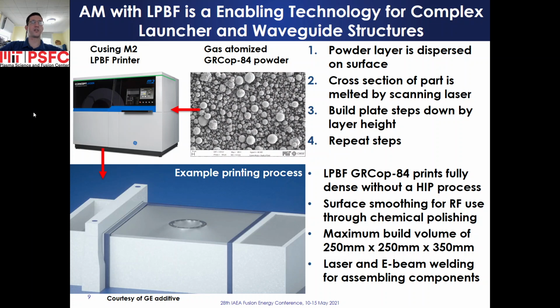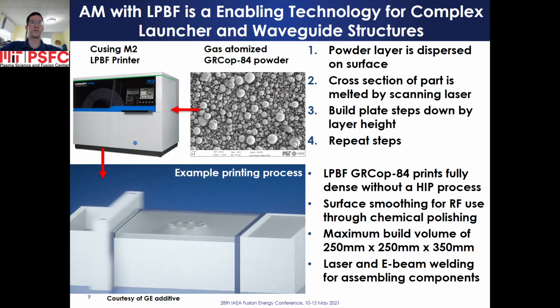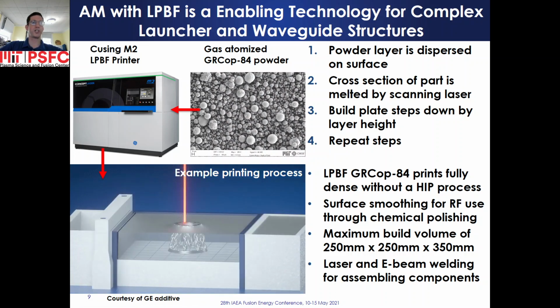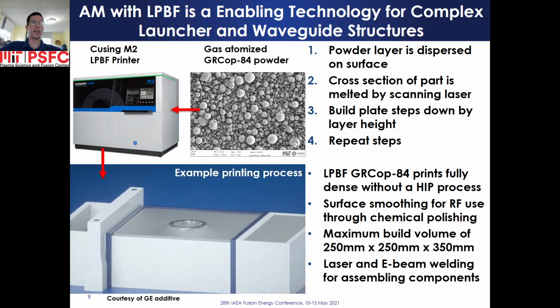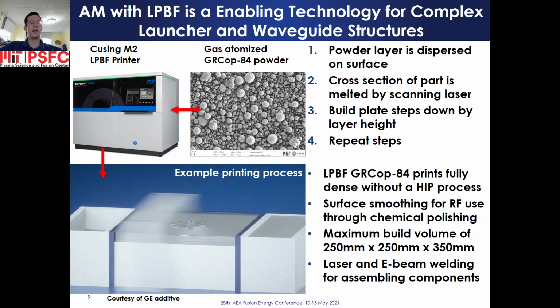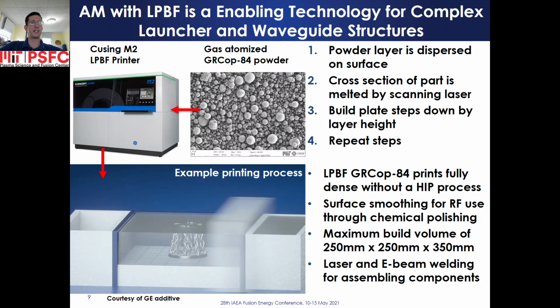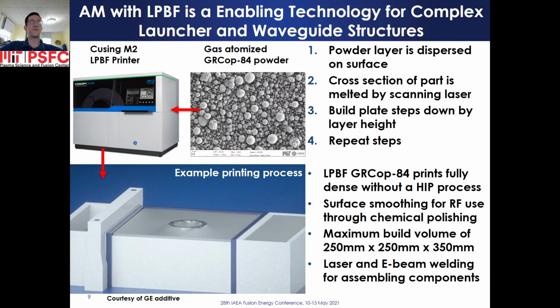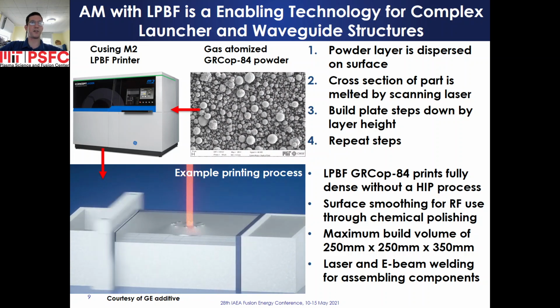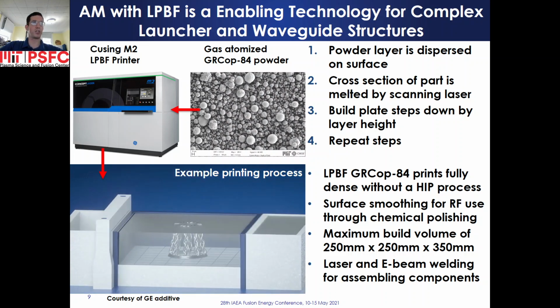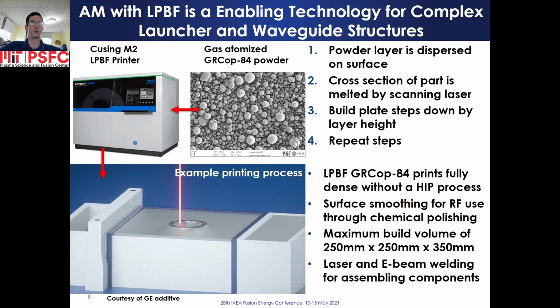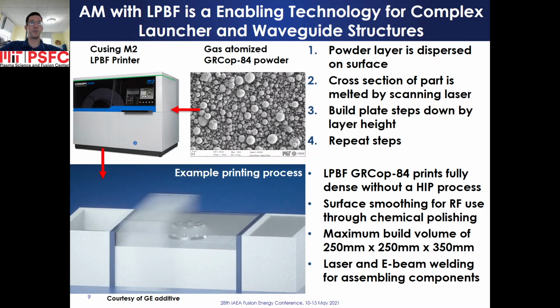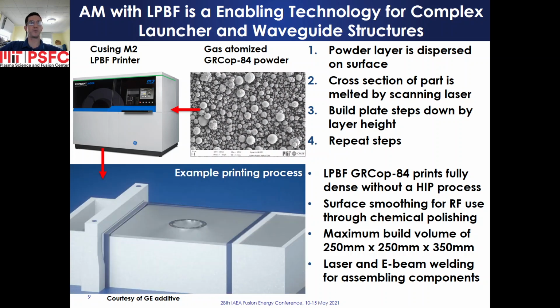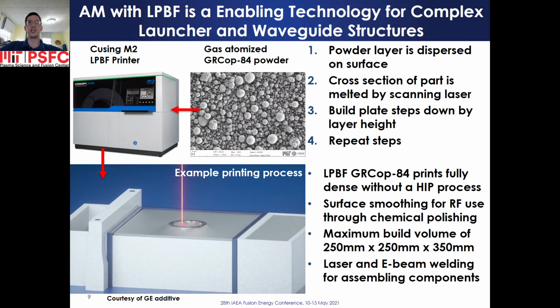Additive manufacturing with laser powder bed fusion is an enabling technology for complex launcher and waveguide structures. A gas atomized powder stock is dispersed on the surface of a build plate with a coater blade. A cross-section of the part is then consolidated by melting with a scanning laser under an inert argon atmosphere. The build plate is then retracted downward by the layer height and the process is repeated. GRCop-84 prints fully dense without requiring a subsequent hot isostatic pressing process. Chemical polishing is used to achieve a sufficiently smooth surface for low-loss RF use. Limitations on build volume require the launcher to be printed in sections and subsequently laser or electron beam welded together.